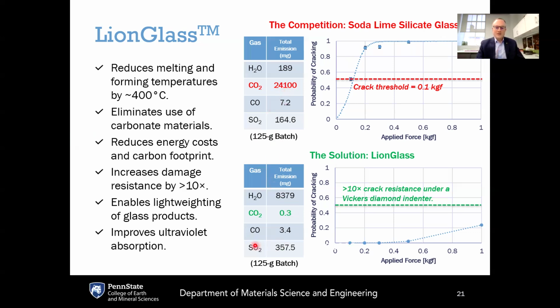Compared to LionGlass, if you see the table on the bottom here, that only has 0.3 milligrams of CO2 that is released as a result of the batch to melt conversion process. And so it is essentially eliminating that part of the CO2 consumption. And then by reducing the melting temperatures by about 400 degrees, this ends up with roughly a 50% decrease in the carbon footprint of glass manufacturing, depending upon, of course, the source of fuel that is used for glass melting.